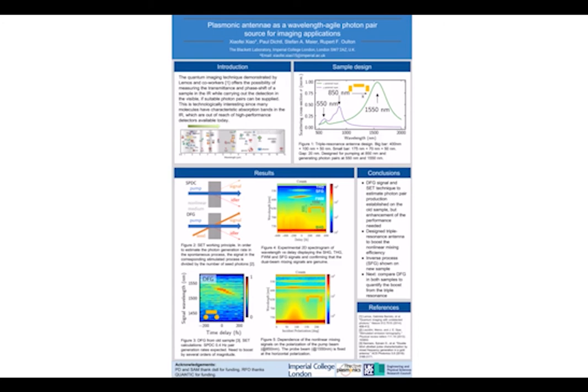On the top right, you can see our design. We have 3 resonances, such that you can pump at 850 nanometers and get pairs at 550 nanometers and 1550 nanometers. Of course, in the future, we would like to push this further into the infrared, where many molecules have characteristic absorption bands. For our characterization, we make use of a technique called stimulated emission tomography, SET.